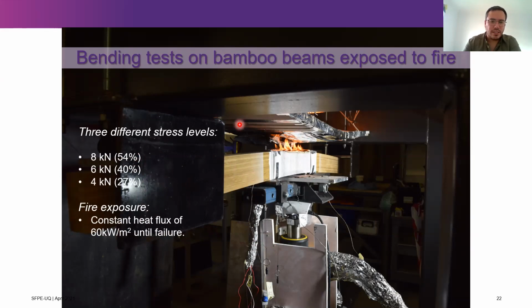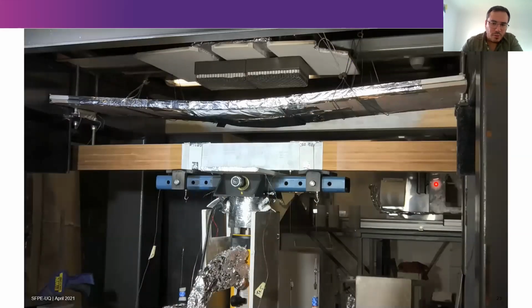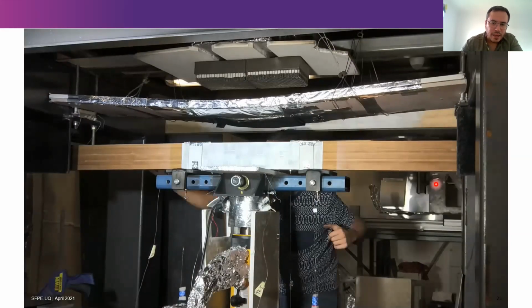We measure the distance between the radiant panels and the beam before starting the test, and that's what defines the heat flux. We ran several calibrations with a heat flux meter, and we were quite confident that we were exposing our beam to a constant heat. So here you will see a typical test.